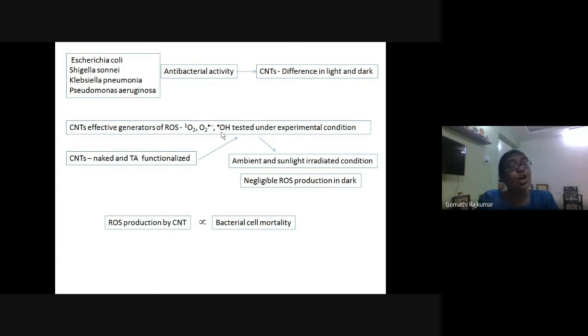In order to further confirm, all of us know that oxy radicals can be counteracted with antioxidants. I hope you all must be knowing this. So now the third part of our work was: if these could generate oxy radicals, let us see if we could coat them with antioxidants, to mask the oxy radical generation. So we took some naked carbon nanotubes, one group, and the other group was tannic acid functionalized nanotubes. Friends, if you ask me why tannic acid: in reality, we chose tannic acid and gallic acid, the phenolic acids. And we also chose quercetin, apigenin, and catechin to functionalize with carbon nanotubes.